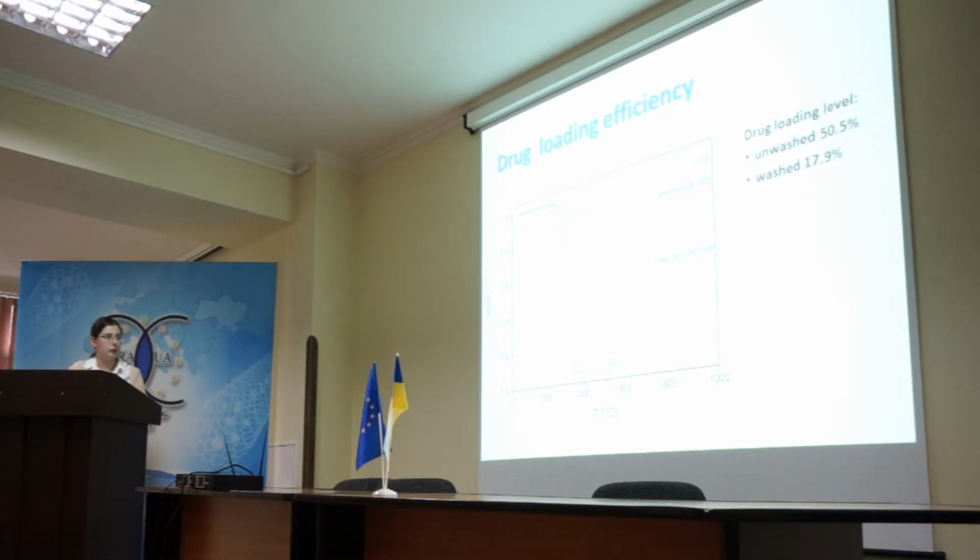For the unwashed sample, we have about 50% of drug loading. After washing, it is reduced to 20%. In order to check whether our drug is in crystalline or in amorphous form, we performed three different studies using three different techniques. First of all, it was differential scanning calorimetry.